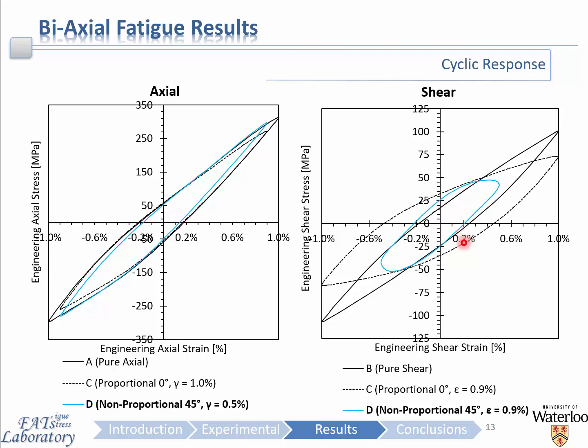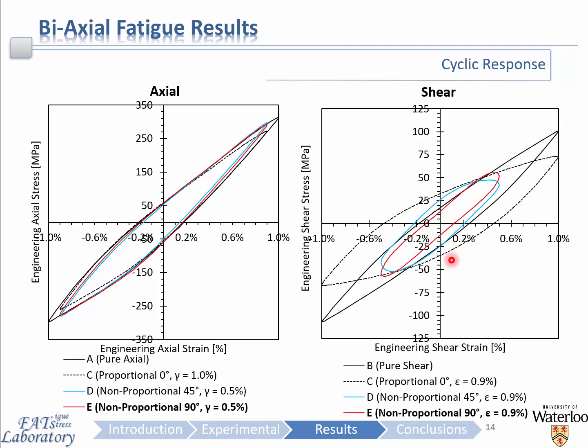Despite this, you can still observe that the shear response remains symmetric, and the peak and valley of this hysteresis loop has become very blunted due to the presence of this axial response on the left. The modification to the cyclic behavior is a direct result of the presence of the axial loading dominating the cyclic behavior, and this is an important concept that will form the basis for the modeling of the fatigue behavior, which I will discuss in a few slides.